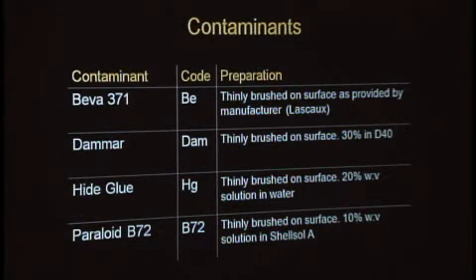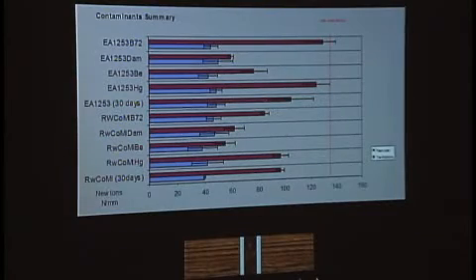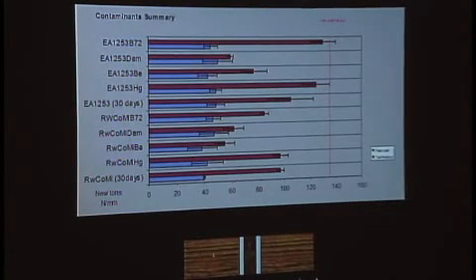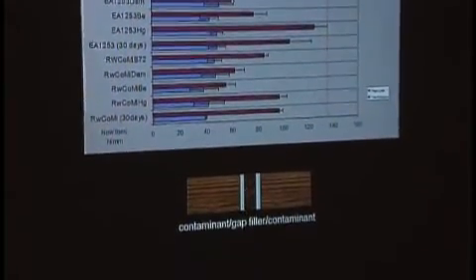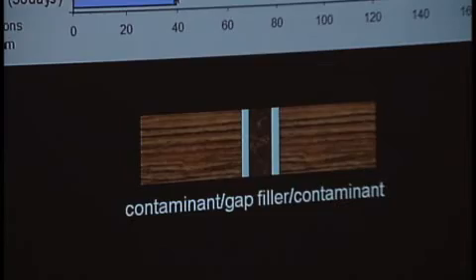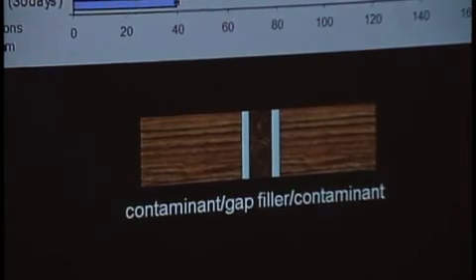So we concentrated on 4 materials, Beva 371, dammar, hide glue and Paraloid B72 as our contaminants within the sample. Just down here is the sample itself. So this is our wood block. The contaminant was brushed on either side, and then the filler was added later. And after 30 days, these were tested at 55% RH.